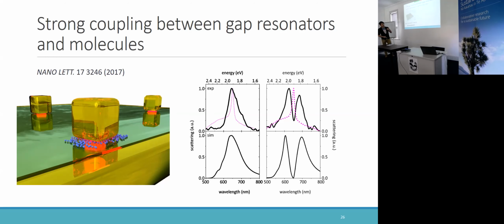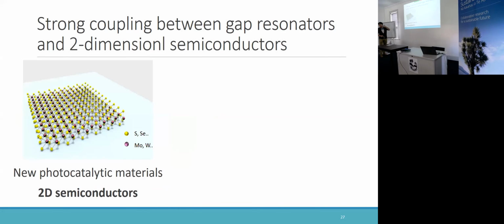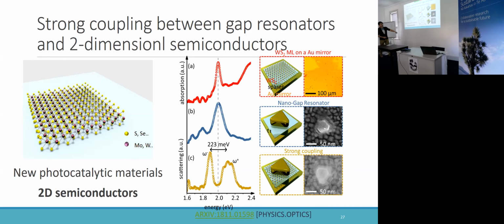So based on these results, now we are working on integrating the 2D semiconductors with single nanoparticles here. This time we don't use a nanocube, we use a nanocrystal because we want to change the frequency to match the frequency of the 2D semiconductors. But anyway, we can also see this splitting here. And the splitting in this case is very large. It's over 200 milli-electron volts, and that is the largest Rabi splitting at the moment in similar systems. Now this paper is being reviewed by PRL, the top journal in physics.